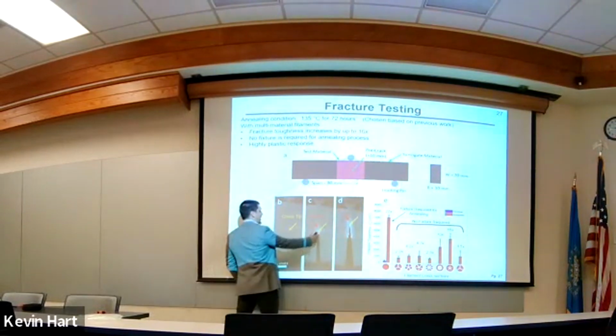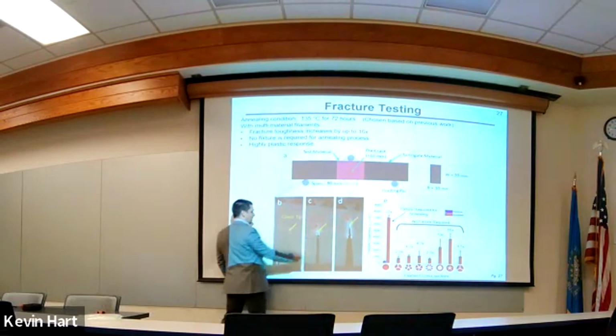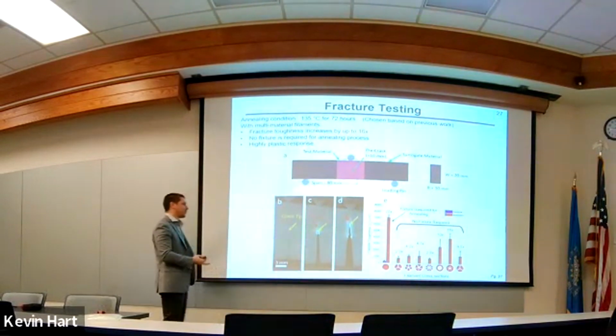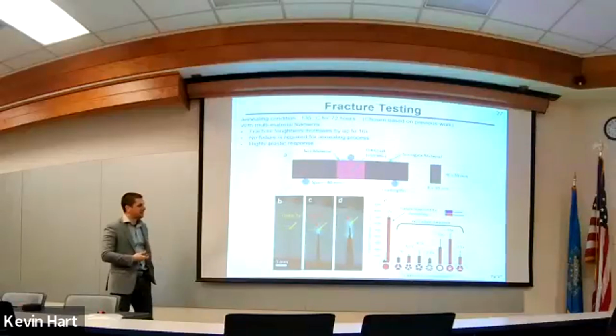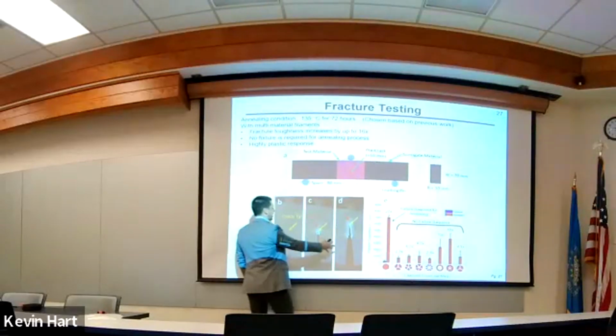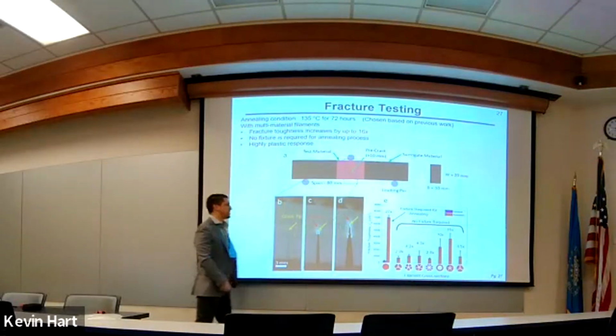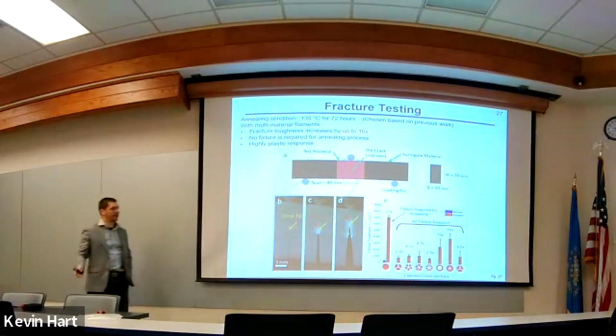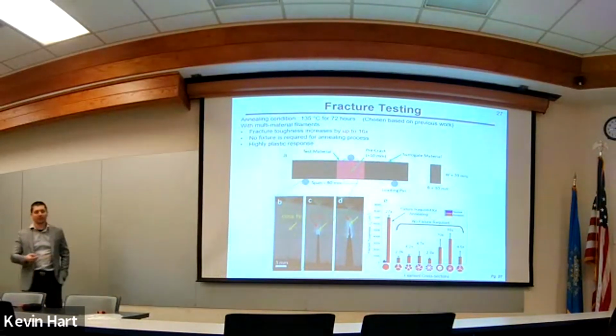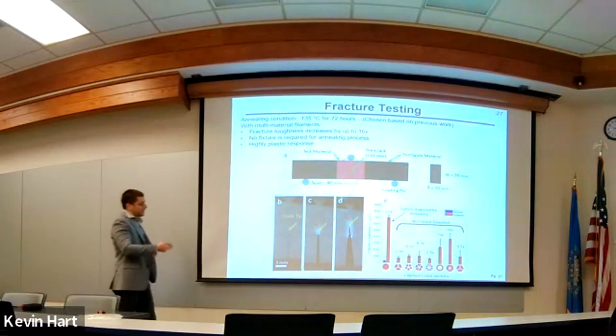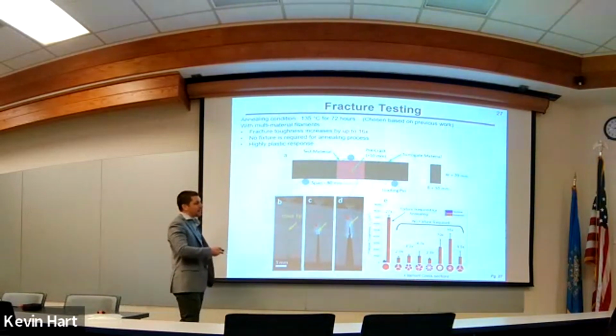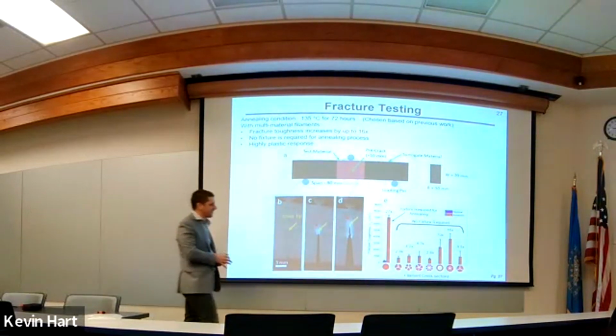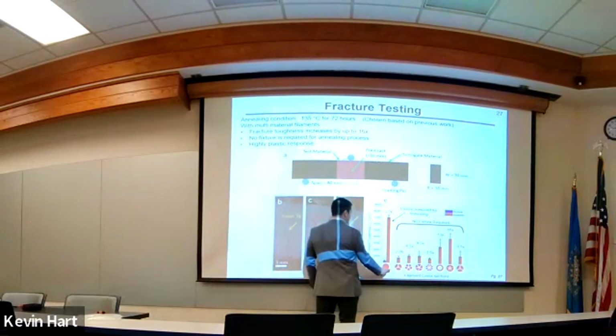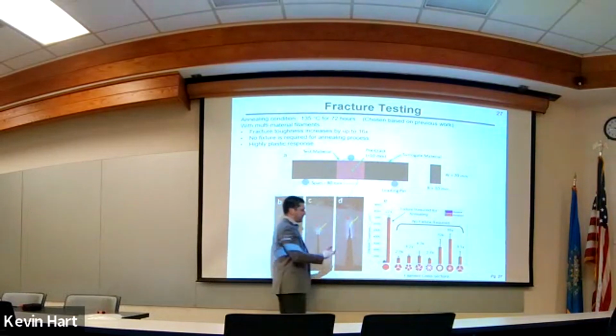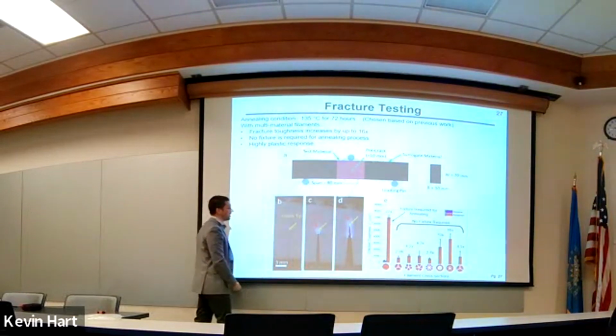Here's the initial crack. The crack is propagating. We see this whitening, which is called crazing, or signs of plasticity inside of the material, and the crack is propagating. We're measuring the energy associated with that crack propagation. We know the area. We can determine our fracture toughness using that. And this is a smattering of a lot of the results that we have. So let's first start with our control, just our blank, typical ABS filament that we've talked about for the first 15 minutes of this talk.